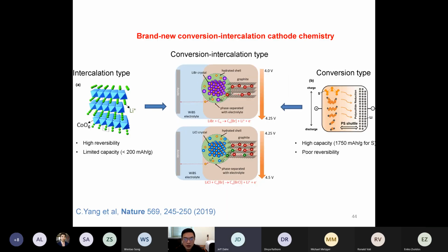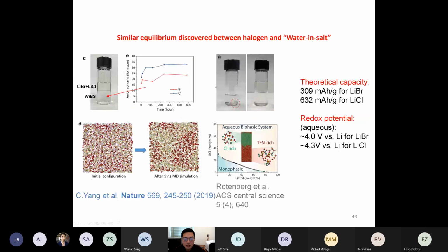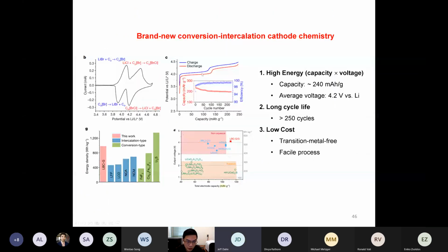We were so excited to see these beautiful profiles, 2-stage profiles, right? Because we had already designed this, we intentionally put the same molar amount of bromide and chloride in there, because we know bromide chloride 1-to-1 will be very stable in the graphite, instead of using all chloride.